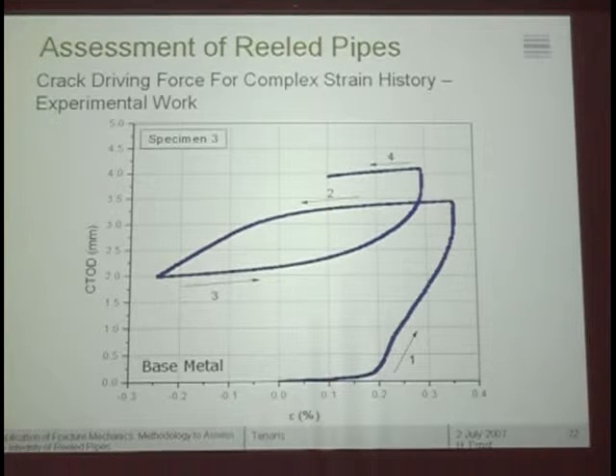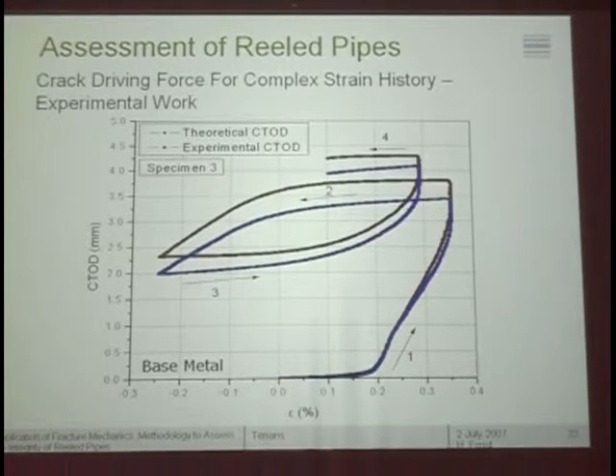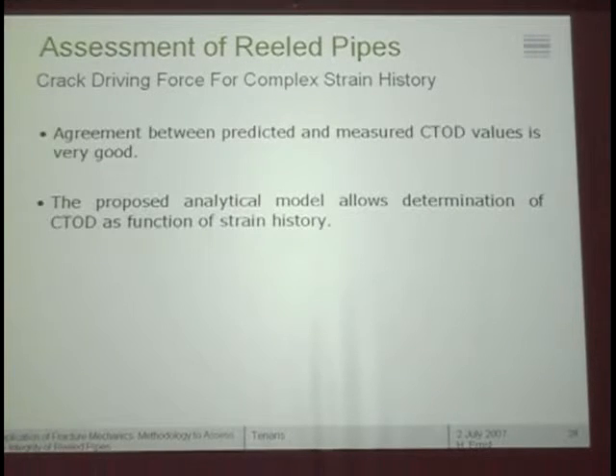So now, applying the model that I just mentioned, this is the type of agreement that we have. In blue, as I showed you before, experimental results. In red, this model that we just presented. We believe that the difference, of course, is there, but it's not so bad. In fact, we are pretty happy, particularly considering the problem that I mentioned before. In both cases, there is some kind of extra elongation in terms of CTOD here that should not be there. So we feel pretty comfortable with this type of agreement. And we want to say that agreement between the predicted and measured CTOD values is decent or very good.